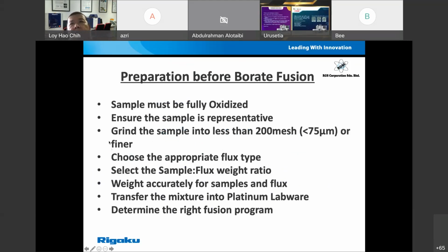Even for fusion, it will be very good, because the smaller the grain size, the easier and faster the sample can be digested or dissolved inside the flux, the lithium borate flux. And you need to choose a proper flux type, because there are many types of borate or lithium flux with different concentrations of lithium tetraborate and metaborate. Then we need to set our sample to flux weight ratio. This is also important, because if the sample to flux ratio fluctuates, then your calibration or measurement results will also give you errors.